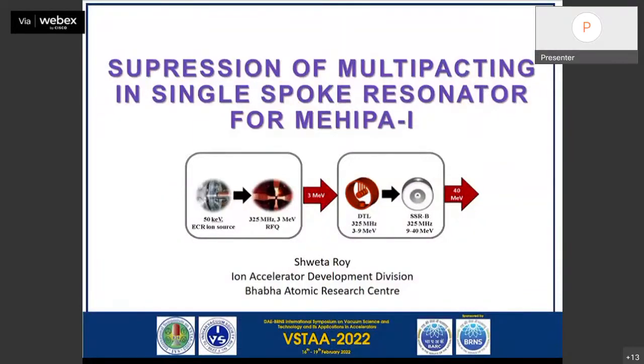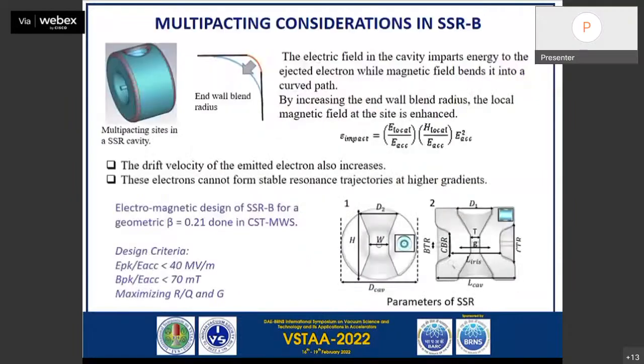The single spoke resonator cavity accelerates the proton beam from 9 to 40 MeV, and it has been designed at a geometric beta of 0.21. Please change. These SSR cavities are prone to multipacting. And the sites of multipacting are highlighted in red in the first figure, as you can see. Here we have proposed to increase the end wall curvature so as to reduce the multipacting at higher gradients, because by increasing the curvature, the local magnetic field is increased at that site, which also increases the emitted electron energy. And so the electrons cannot form stable resonance trajectories at higher gradients.